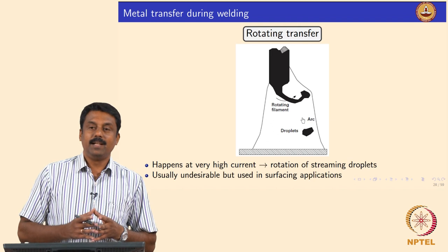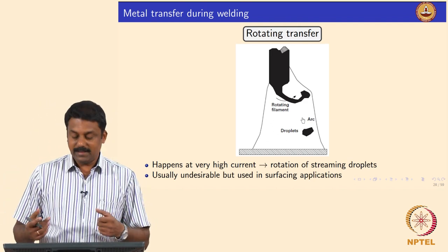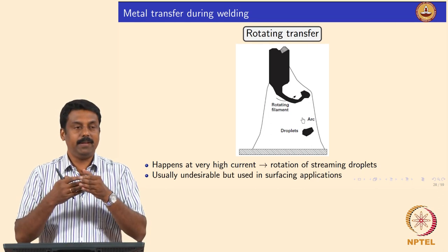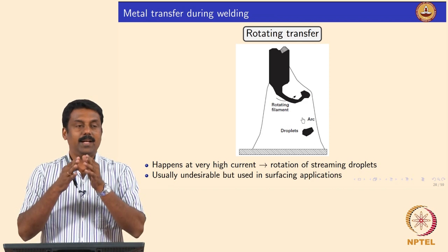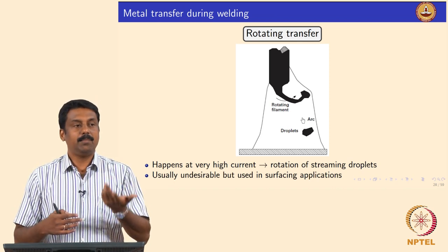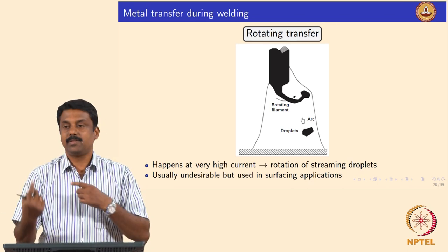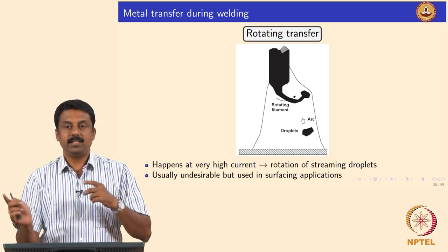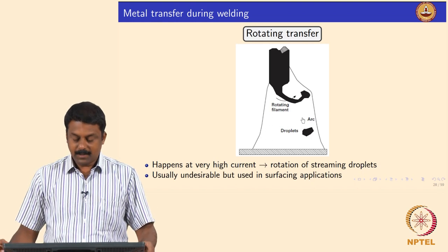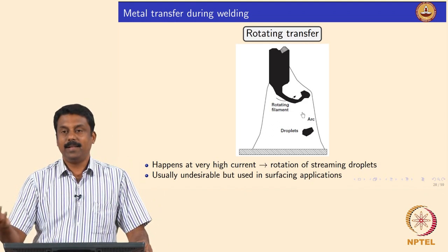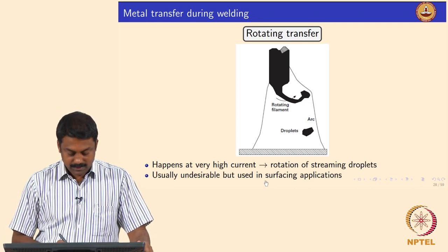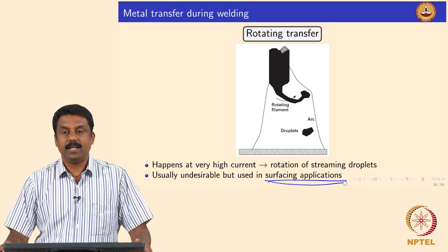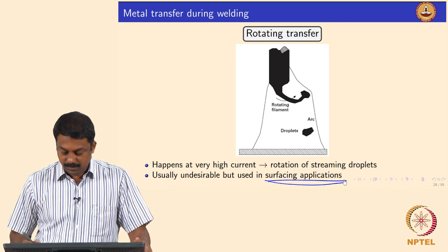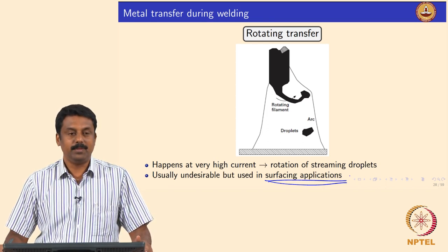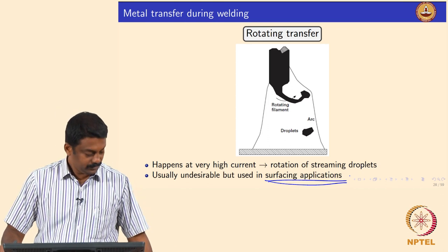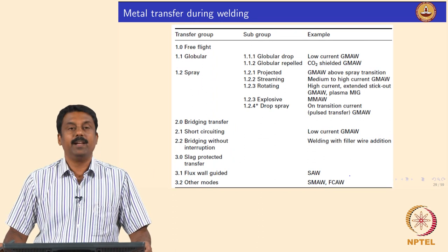If you sometimes increase the current, a jetting spray becomes rotating transfer. The reason is the same as I told you: if you start making a jet and you have a Lorentz force continuously forming, certain magnetic forces start rotating or changing the path of the spray, and you will have a rotating spray transfer that goes everywhere. So you end up transferring the droplets at various places. Again, this is also sometimes used for surfacing, using FCAW or GMAW surfacing. For welding applications it is not advisable. Right, it's clear, good.